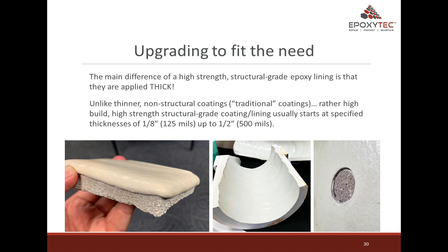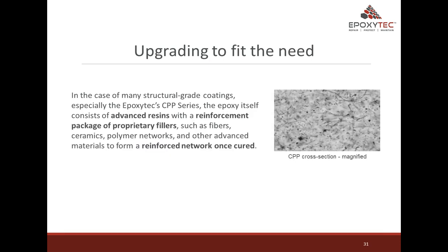The main difference of high-strength structural grade epoxy linings is that they are applied thick. Unlike thinner non-structural coatings or traditional coatings, high-build, high-strength structural grade coating linings usually start at specified thicknesses of 1/8 inch, which is 125 mils, up to 1/2 inch, which is 500 mils.